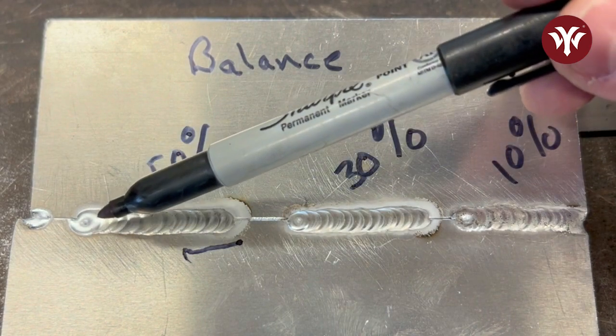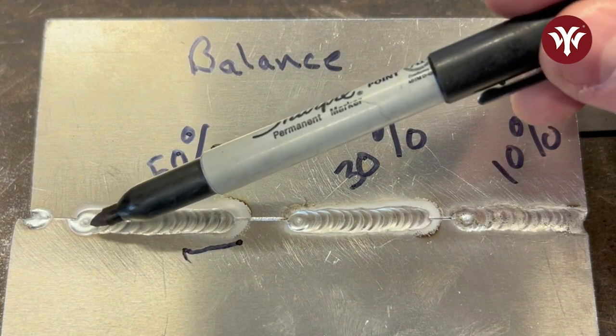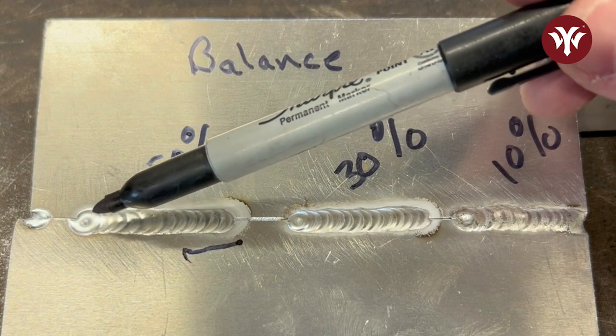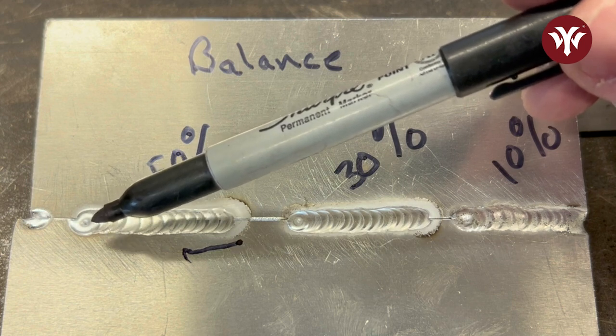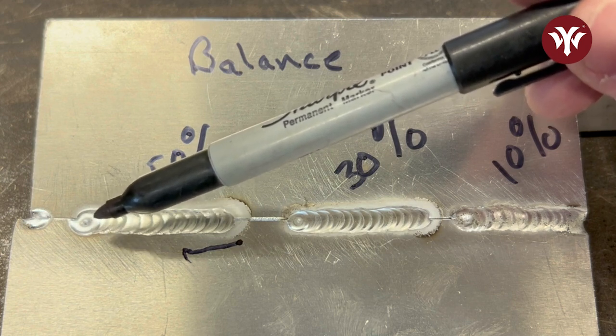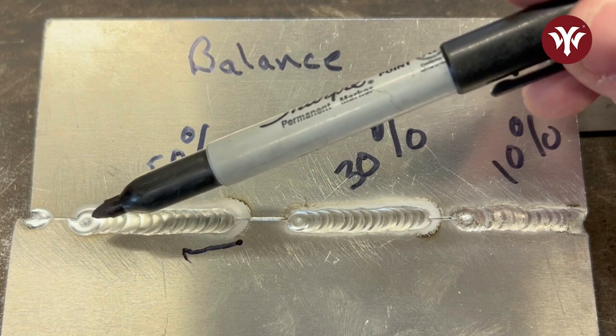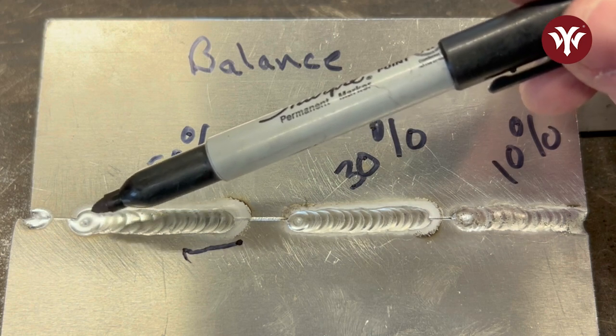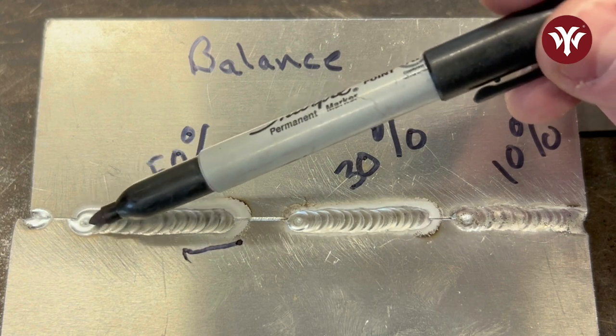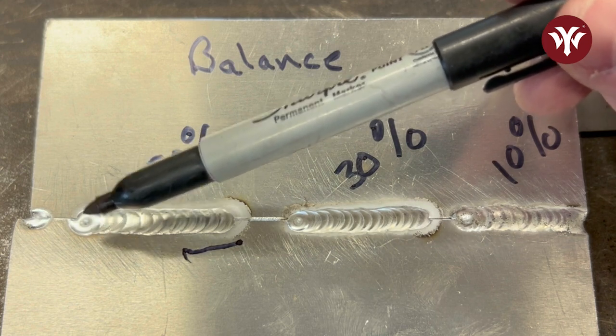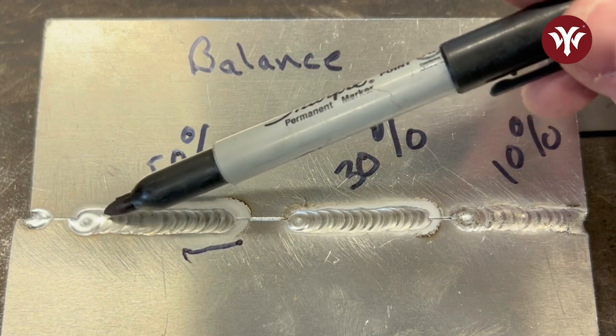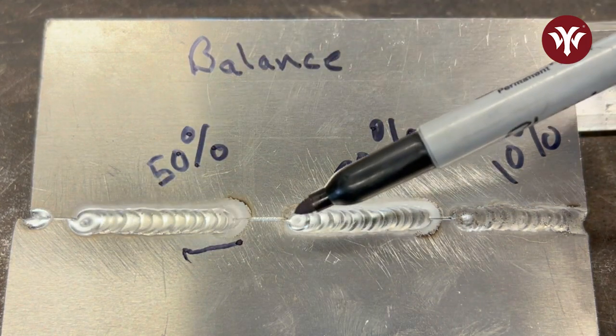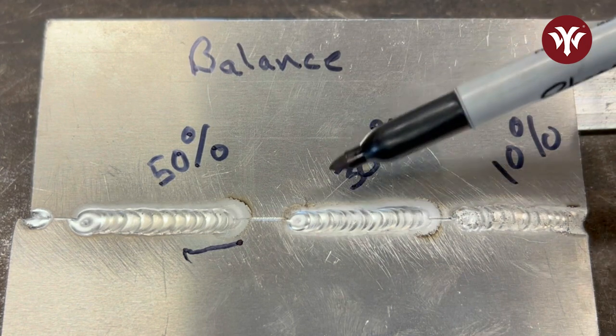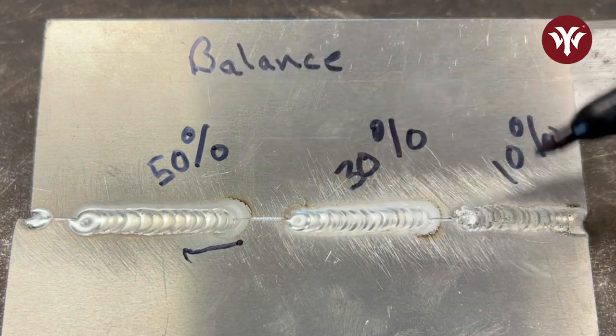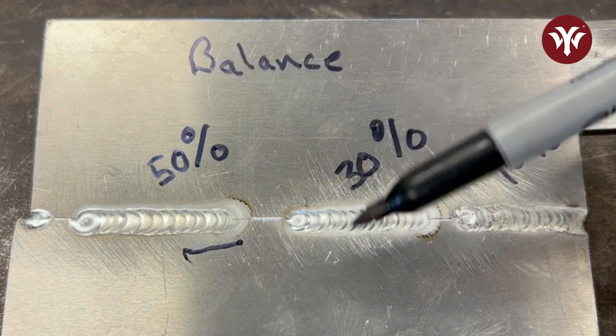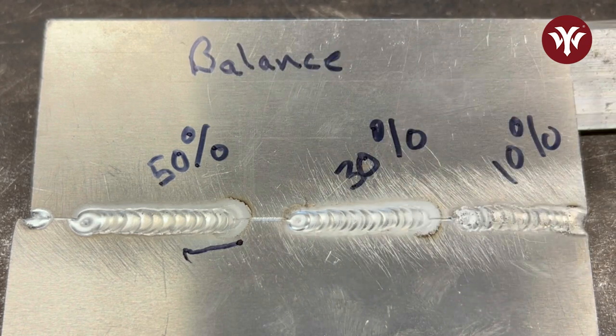I didn't really crater fill this, so you can see that little hole there is the crater we're talking about when you finish a weld. The best way to fill that is to slowly ramp down the current with your foot pedal while giving it just a little bit of an extra dab of filler rod at the end. Let the puddle fill in, because that little crater there can very easily lead to a crack migrating down the weld. And here I did crater fill it. So there's a little bit of a difference. I hope that explains what balance is and the effect of adjusting that balance.